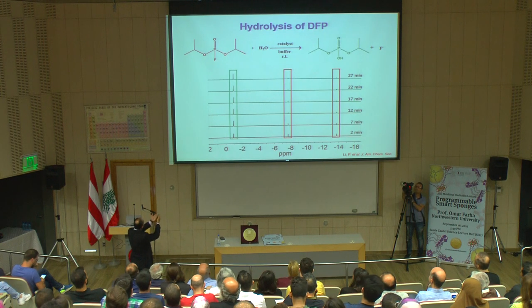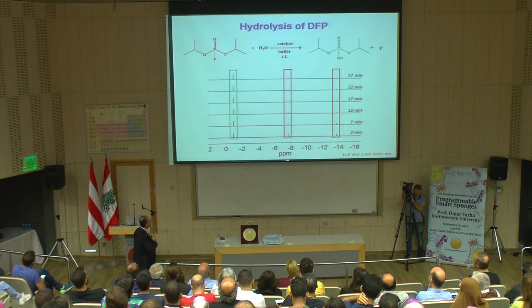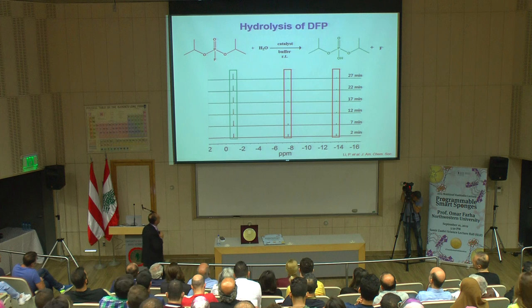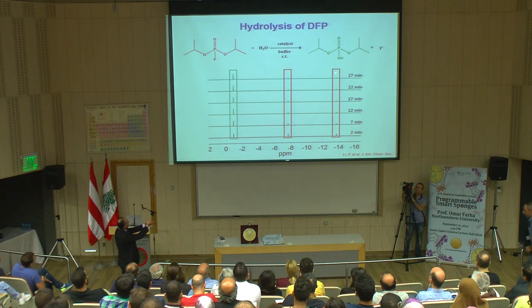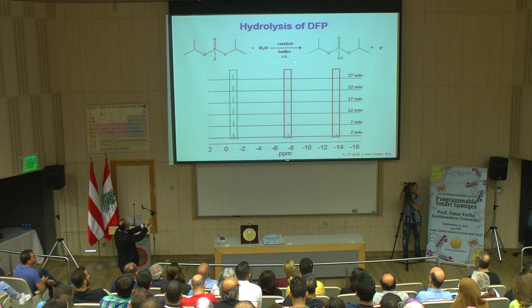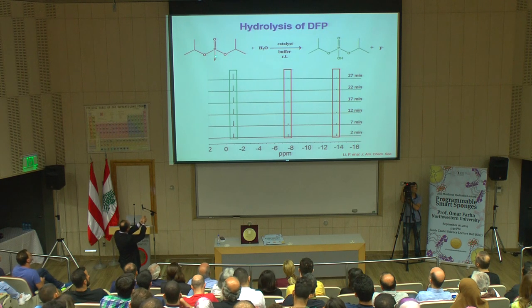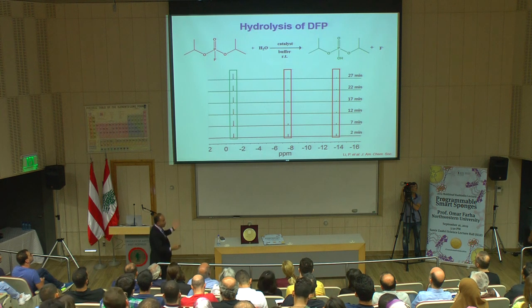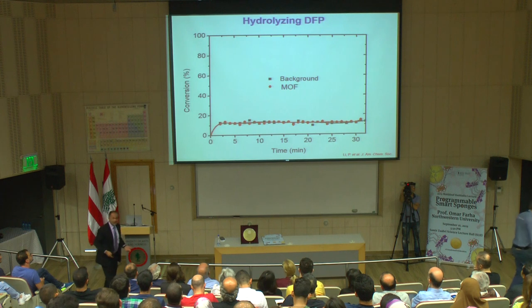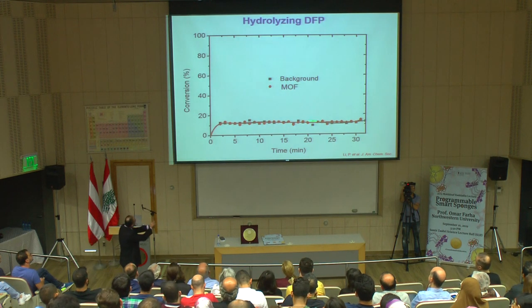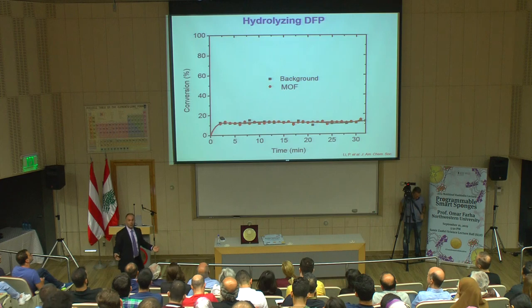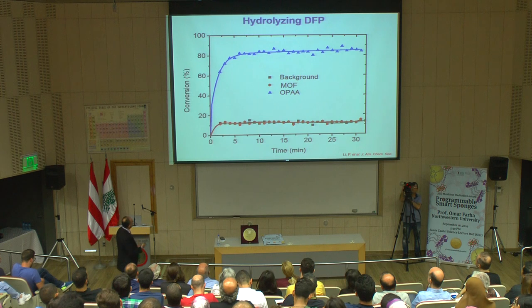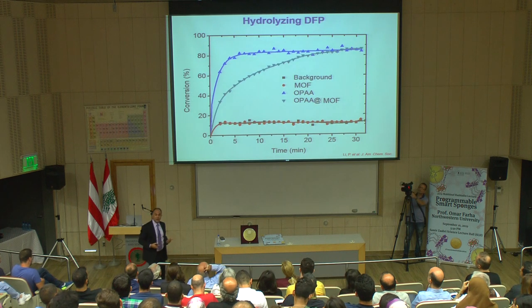This is what we used as a less toxic material, and we could actually see that the catalysis works quite well. And you could see from the phosphorus NMR that you have two peaks for the starting material because the fluorine split the phosphorus, and you only have one peak for the OH. Everything now makes sense. When we test this composite, that's what you see from the background. That's from just the water, the buffer, or the MOF itself. This is the free enzyme, and when you do the composite, that's what we get.